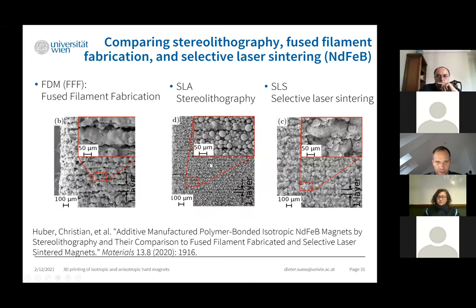If we look at the inner structure, we also see that the neodymium iron boron spheres are perfectly still preserved in these SEM images in the stereolithography case. For fused filament fabrication, we also see the agglomeration with the polymer. And for the selective laser sintering, we see that partly the neodymium iron boron spheres are melted.